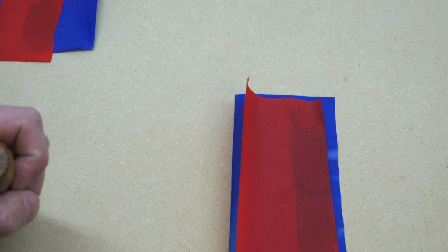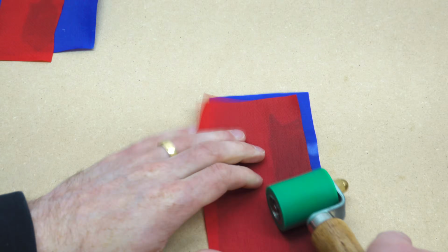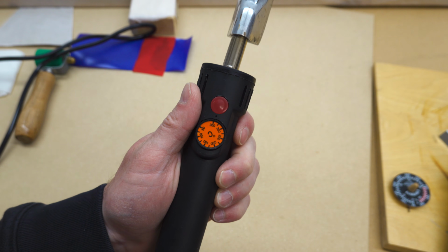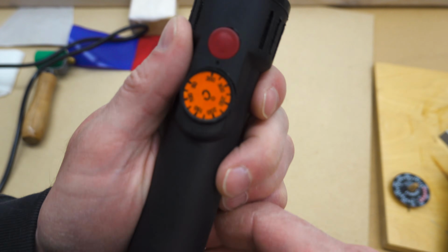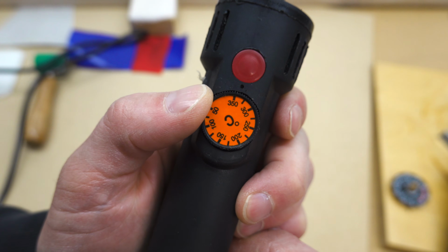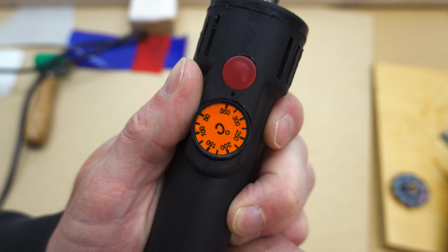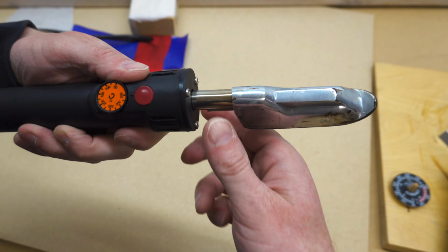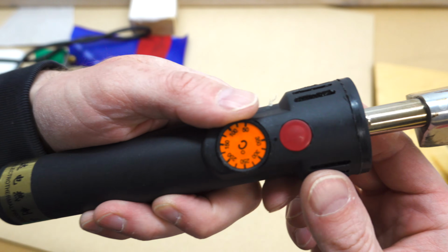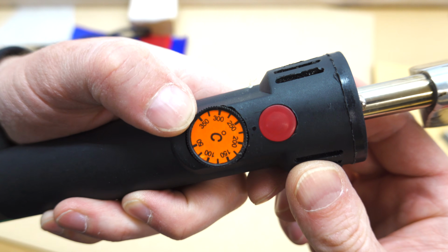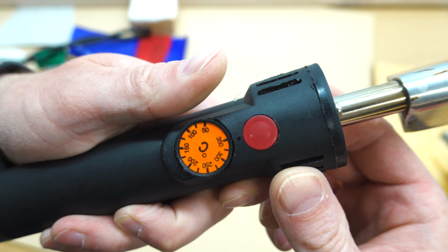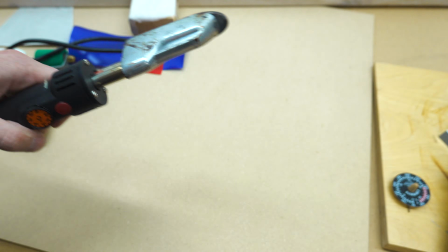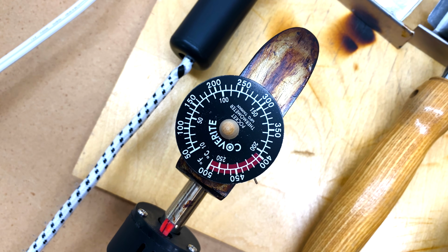Knowing that number doesn't really help you at all, because you can't rely on the numbers on your iron's adjustment dial to set the temperature. To illustrate this point, this particular iron works best when set to 350 degrees Celsius, but if that was the actual temperature at the surface of the metal, then the iron would melt right through the fabric. So this iron is much cooler than it indicates. It's literally off by 150 degrees.